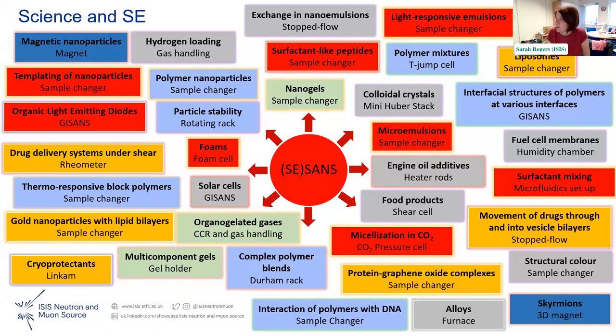So just to give you an idea of not only the science, but the sample environment that we have available, we have a really broad range of stuff that you can do to your sample. So we can obviously look at things like magnetic nanoparticles, using very large magnets, anything from half a tesla, probably even smaller, up to, I think the biggest we've ever had is 14 tesla. So we have quite a range of magnetic fields. We obviously have sample changers, kind of standard solution scattering. We can do grazing incidence measurements where we reflect off the surface, sort of do SANS from a surface. We can do rheology, so looking at systems under shear. We can do that on the beamline.